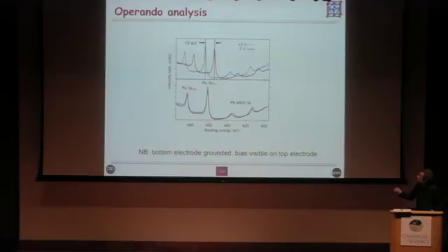Here are the raw data. The two bias states we used were +3 and -7. That was because, you remember the electrode characteristic, there was an offset. There was a 2-volt offset. So these values are actually symmetric around that measured butterfly loop. So the spectra are offset by 10 volts. If you correct for that, then of course the electrode core levels coincide, but you can see here there are residual differences in the emission coming from the PZT. And these residual differences are therefore due to the polarization state affecting the PZT near the interface.